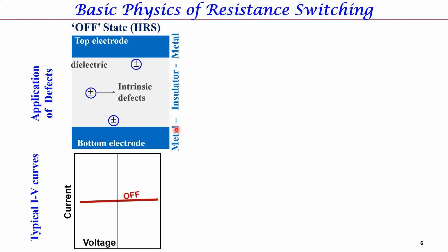They're MIM, or you could say a capacitor structure. Of course, the insulator is non-conducting, so if you try to measure current flowing from the top electrode to the bottom electrode, you see virtually zero current. So we say this is an off state, a high resistance state. Even though you may have defects, these defects themselves may conduct, but because they don't create a path for current to flow, the device is off.